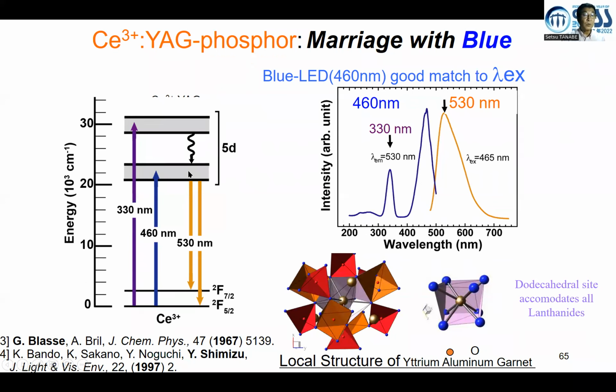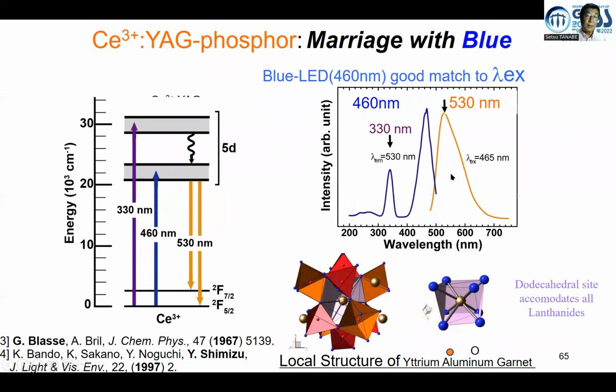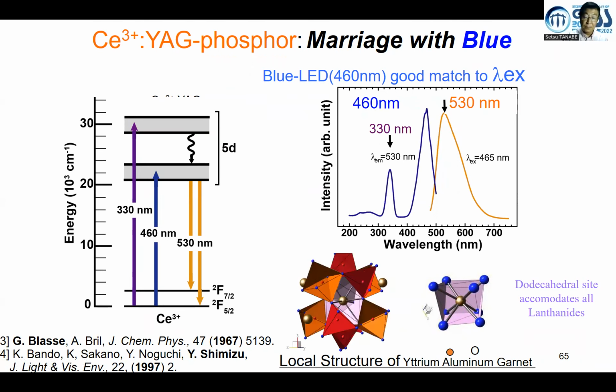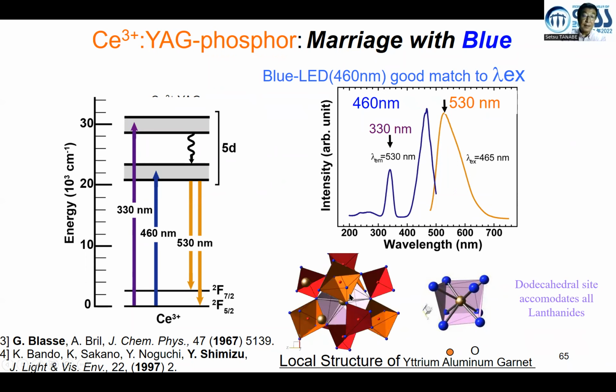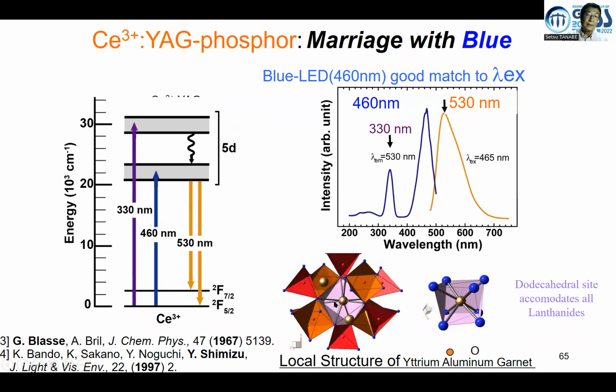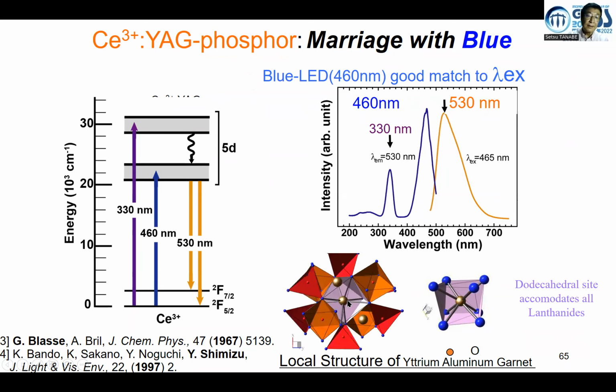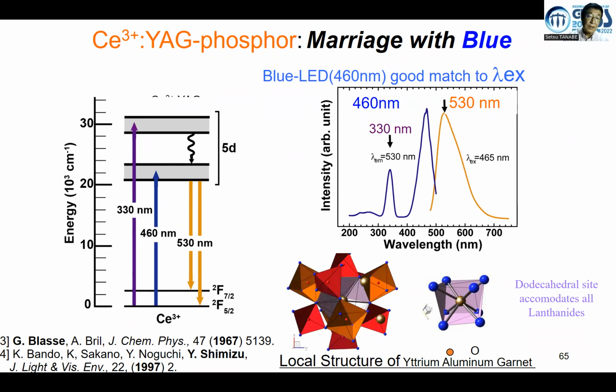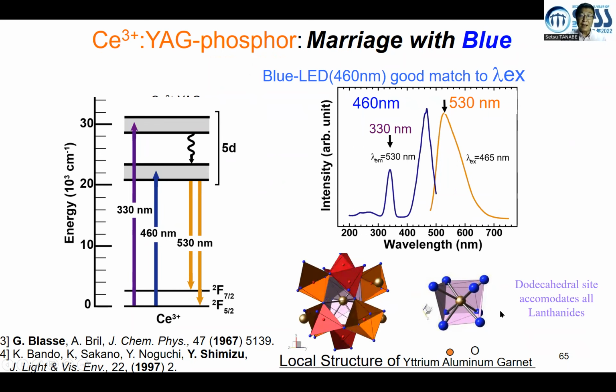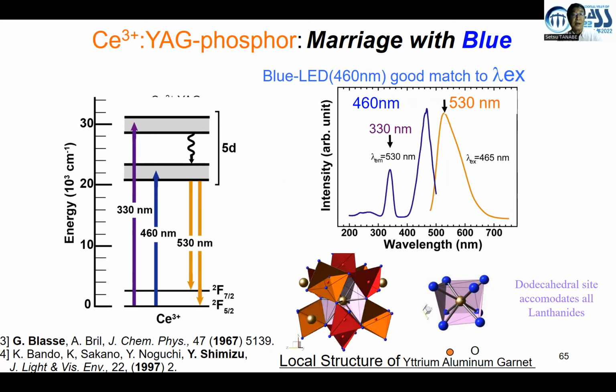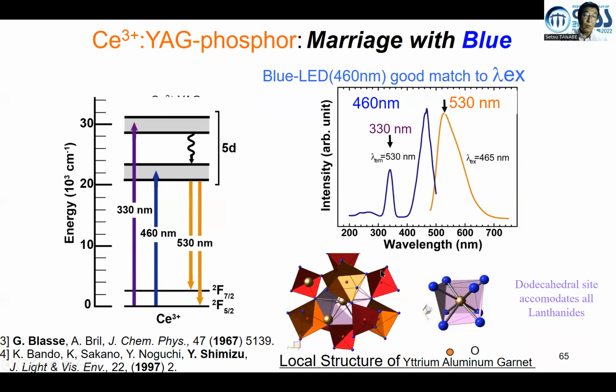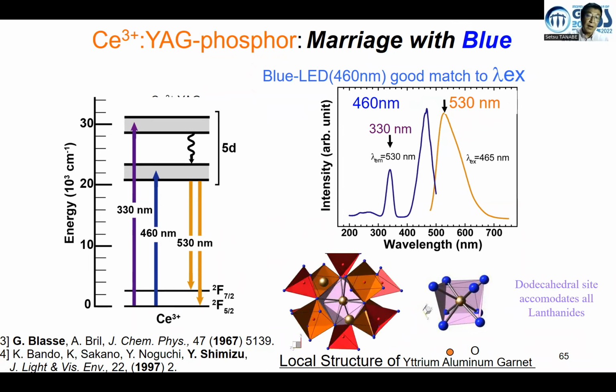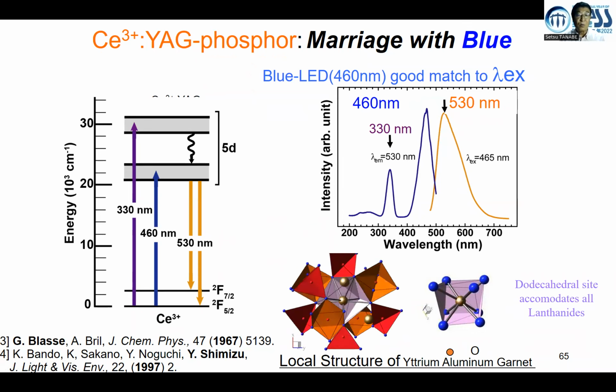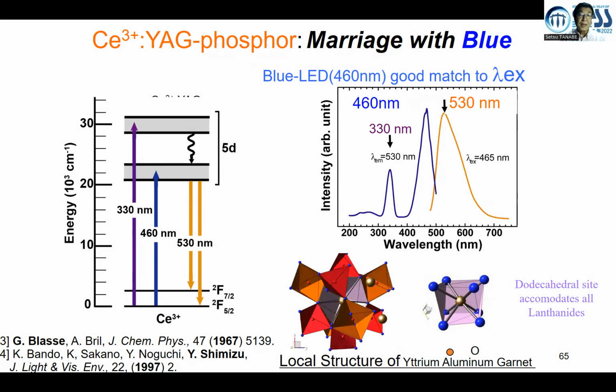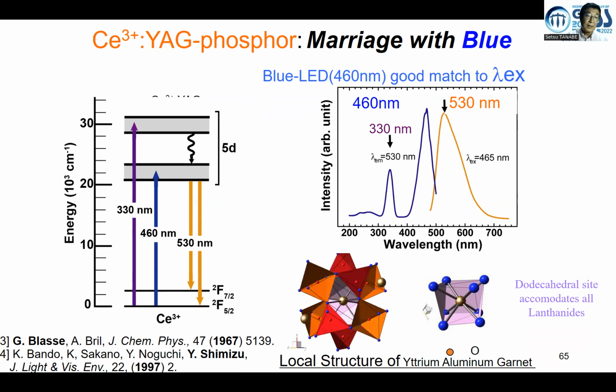At the same time, due to the Stokes shift, luminescence appears at slightly longer wavelengths because of the broad 5d-4f transition. And this is a local structure of garnet crystal. The yttrium site in YAG, yttrium aluminum garnet, the dodecahedral site, can accommodate any kind of lanthanoid elements. The octahedral site can accommodate scandium or aluminum or gallium. The tetrahedral site can accommodate gallium, aluminum, and sometimes silicate material.